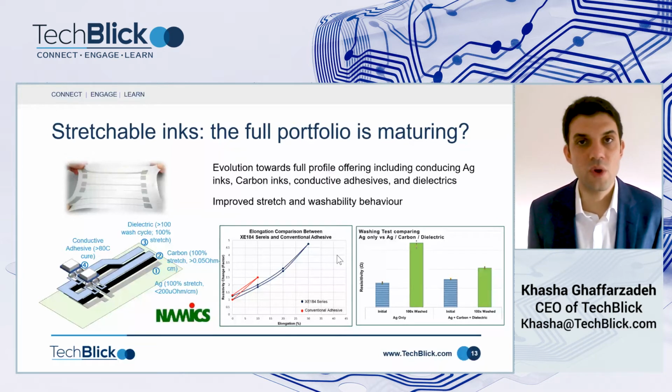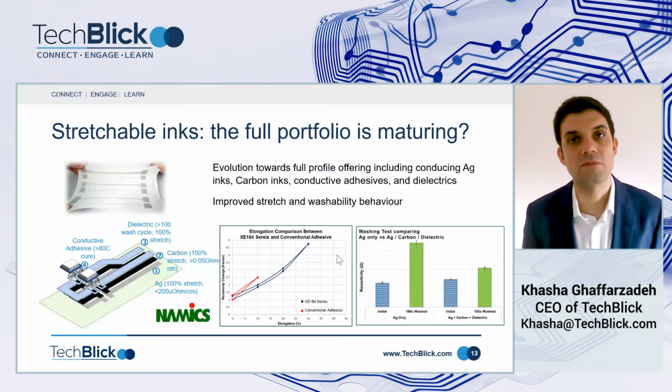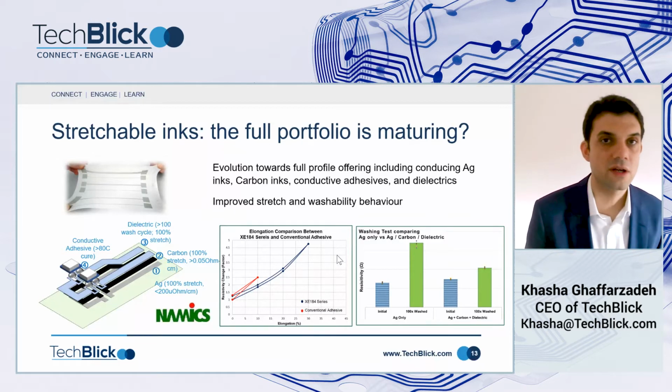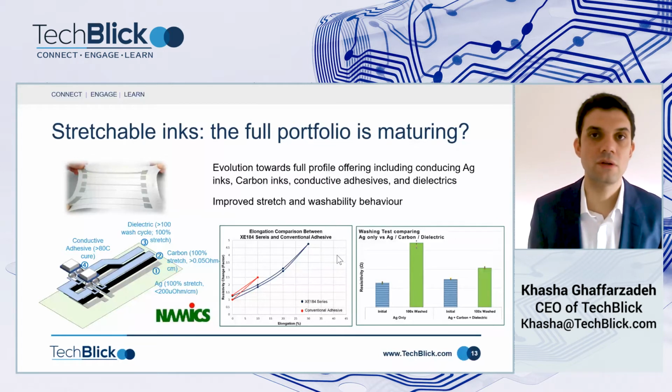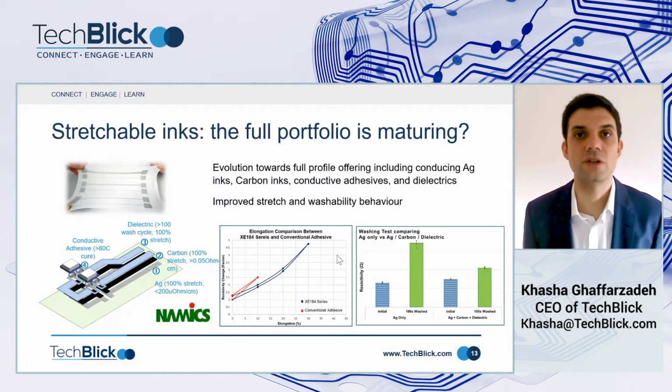But when you have a stack, you are making it more washable. And in this case, you can see that after experiencing 100 washing cycles, the stack of materials has performed better. It has experienced a smaller amount of change in the overall resistance.